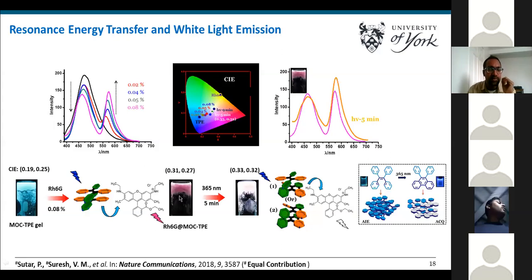This pink gel, when it is spread on a substrate, looks white, but it is not really pure white. To get a pure white light, we irradiated this pink gel with a 365 nanometer laser source for 5 minutes. The idea is that the pink gel has these tetraphenylethene molecules. When we irradiate this system with a 365 nanometer laser source, some of the TPE converts into diphenylphenanthrene, which is strongly blue emitting. The blue emitting part adds to the pink emission, so we ultimately see a further broadening of the emission spectrum covering the whole visible spectrum, and thus we create a white light emission.